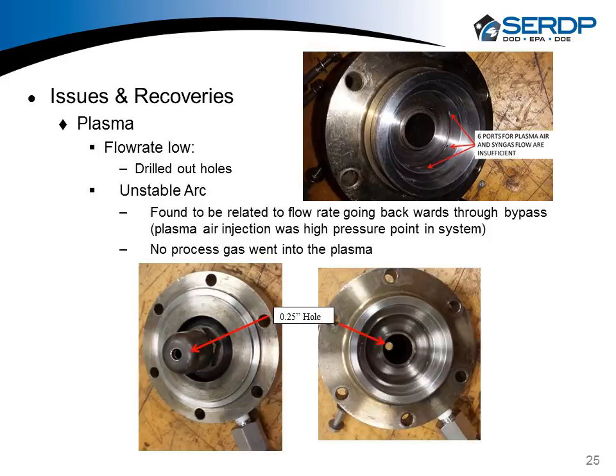Hard to recover from. The other thing we were noticing too was the flow rate was low. I discussed extensively with the guys at Drexel what we should do, and we did get okay to put an extra hole in the thing to allow gas flow. Originally it was coming out of these small ports, and we couldn't get enough flow to really even detect it in our flow rate system. So unless we were really drawing a super vacuum that was overloading the compressor and everything, we couldn't get enough flow through this to do much.